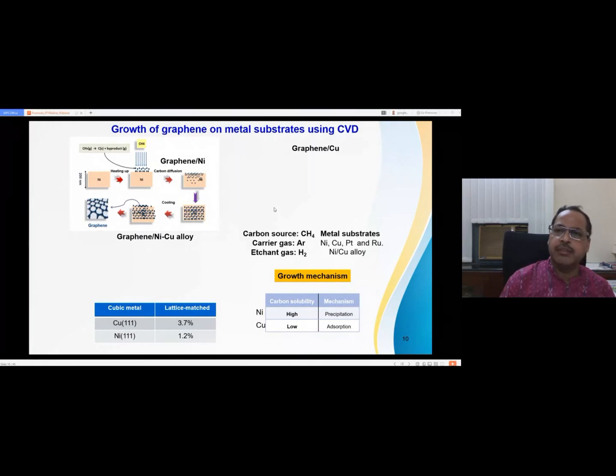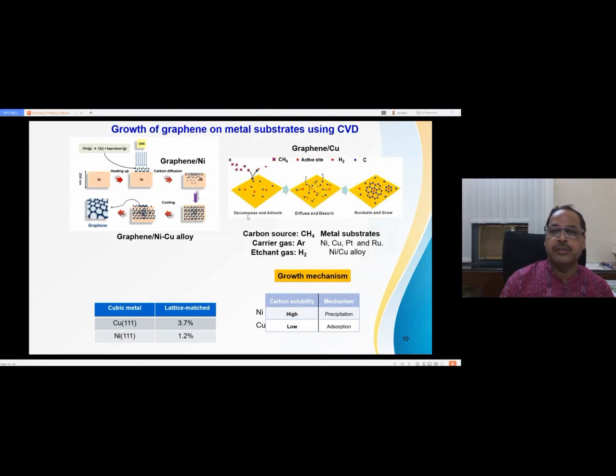So the most reliable synthesis technique is graphene on copper. In graphene on copper, what do you do? You take a copper substrate and again put it into the CVD chamber. Similarly, the CH4 dissociates into carbon at elevated temperature, more than 800. There are decomposition and surface adsorption. There is no surface precipitation because the solubility is very low. Then it diffuses and there is some desorption. Then you will find some nucleation sites. The grain boundary acts as a nucleation site and it starts to grow.